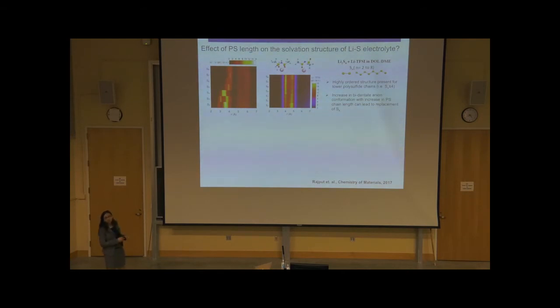We also looked at the radial distribution function of LiTFSI, and we found that there are two peaks. The first peak contributes to the bidentate configuration of TFSI, where TFSI can donate two oxygen atoms to this lithium. And the second peak is for monodentate configuration, where it donates one oxygen atom. And as you increase the chain length of these polysulfide species, the intensity of bidentate configuration increases at the cost of monodentate configuration. So again, as we increase the chain length of polysulfide species, due to more oxygen coordination, it sort of kicks out the polysulfide species from the first solvation shell around lithium and increases the solubility of larger polysulfide species.